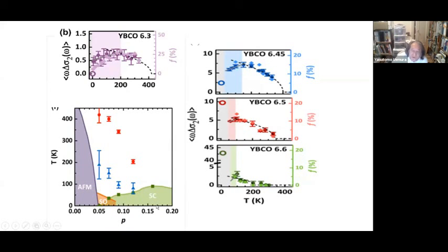Nevertheless, Andrea just plotted, in their publication, this onset temperature. And if you do that against nominal concentration, then you will see that the onset temperature follows T star. In this case, therefore, the boson formation temperature. And this story is somehow different from what I have tried to advocate up to now, that this phenomenon should be following this local phase coherence buildup.